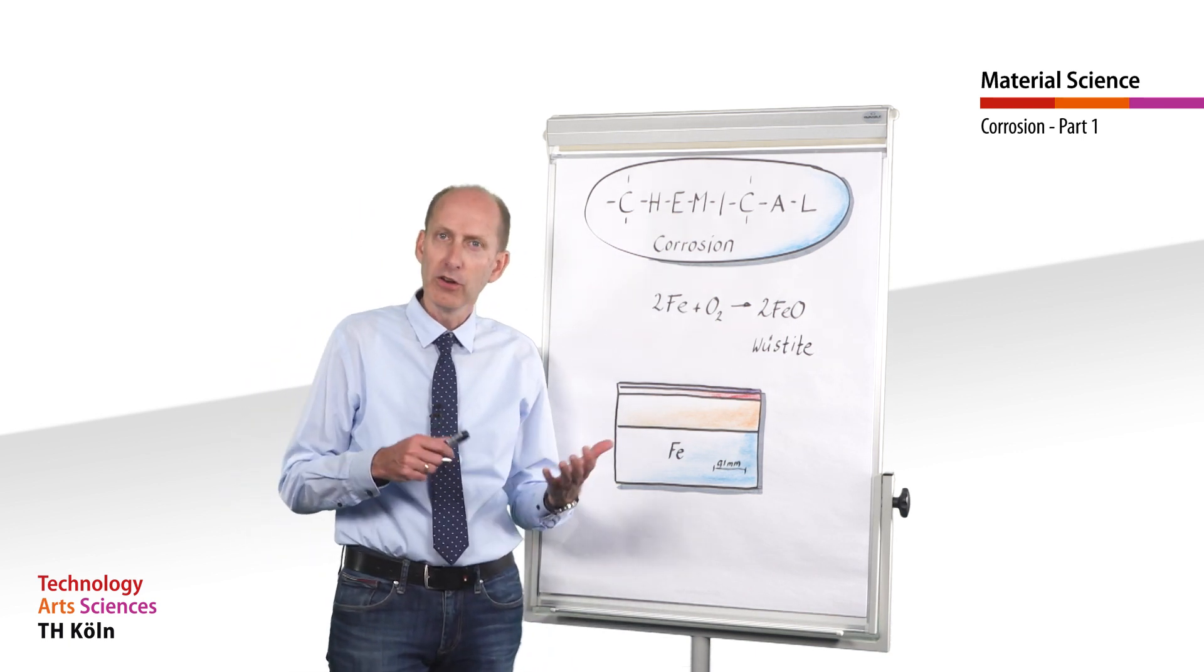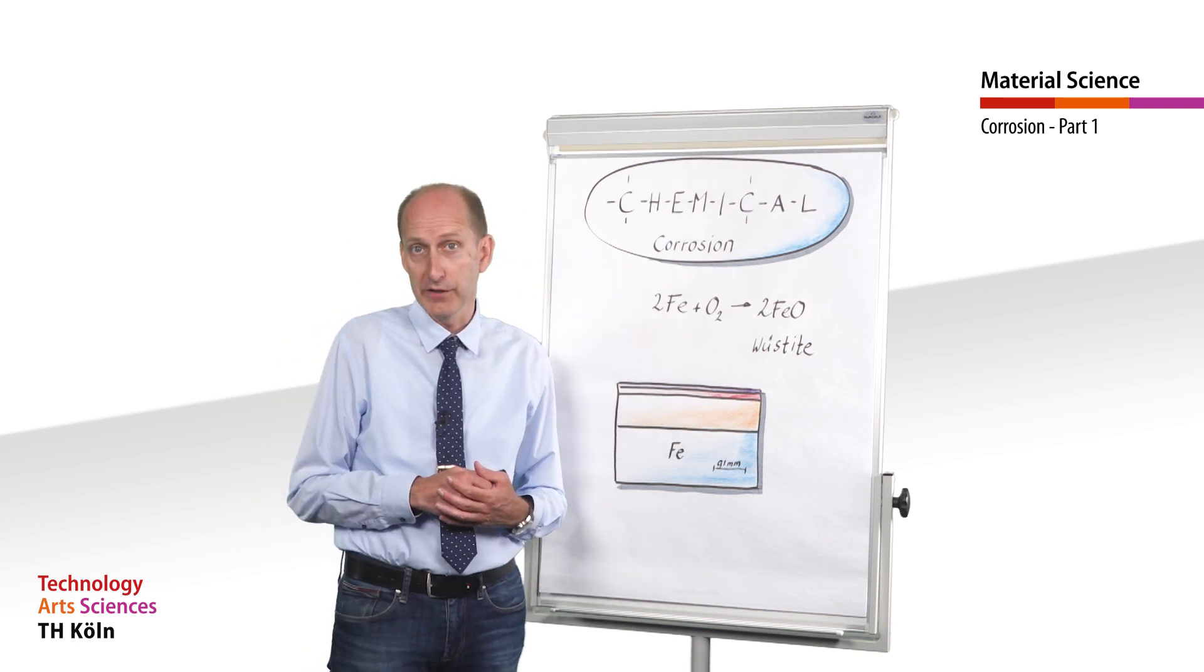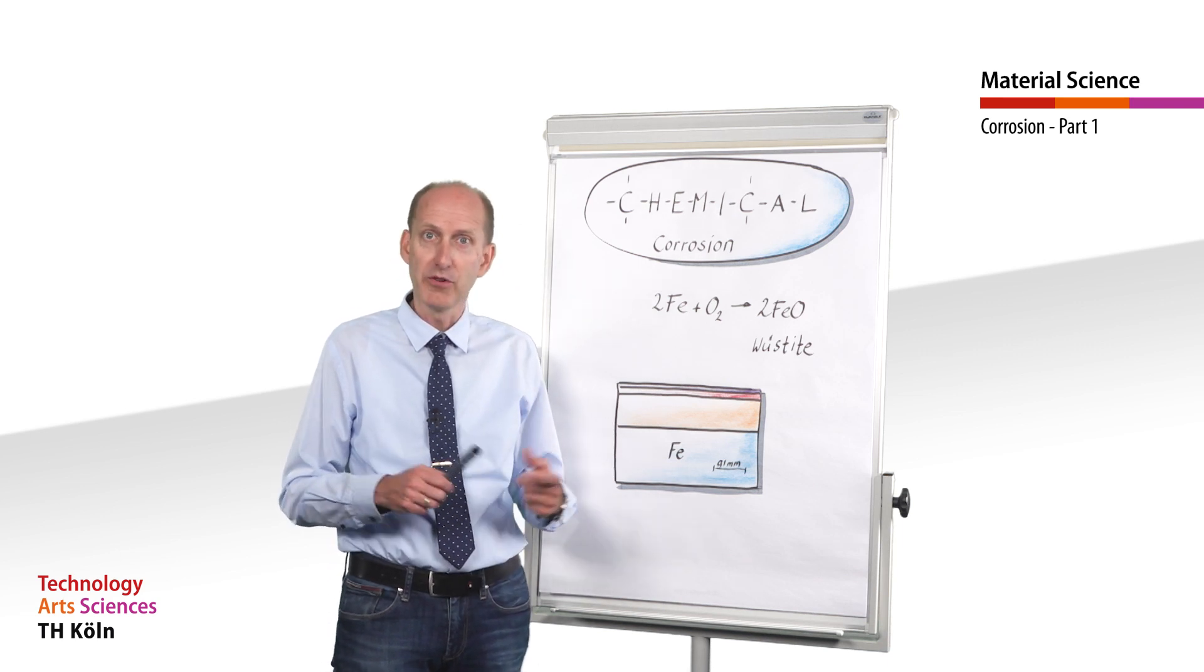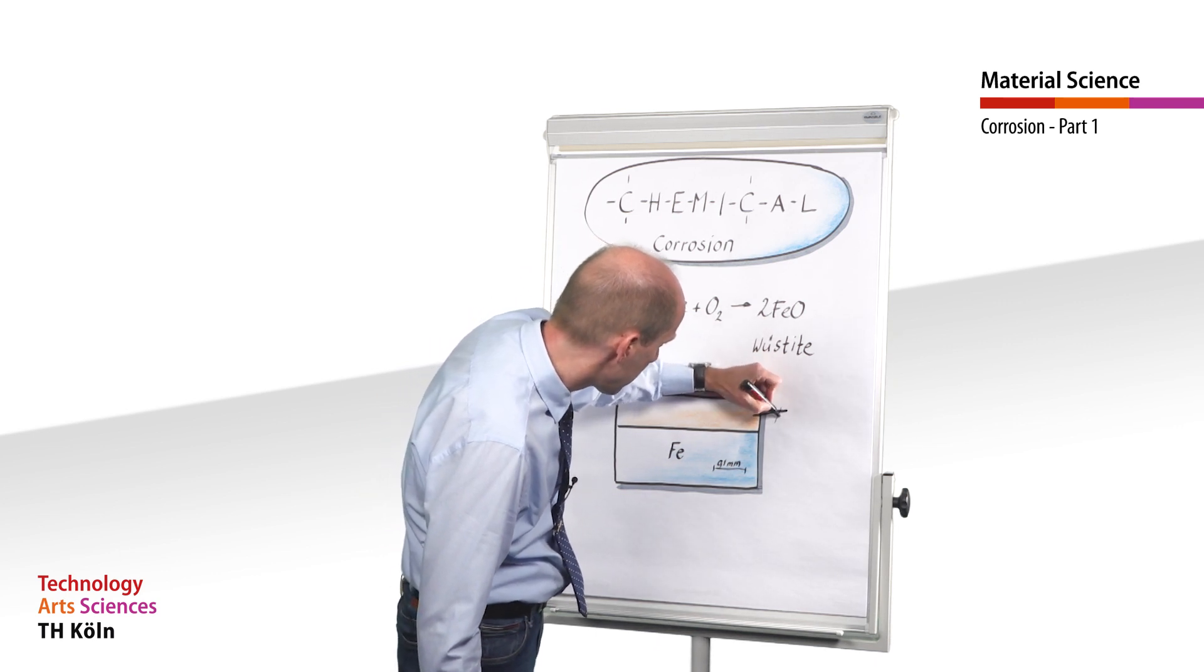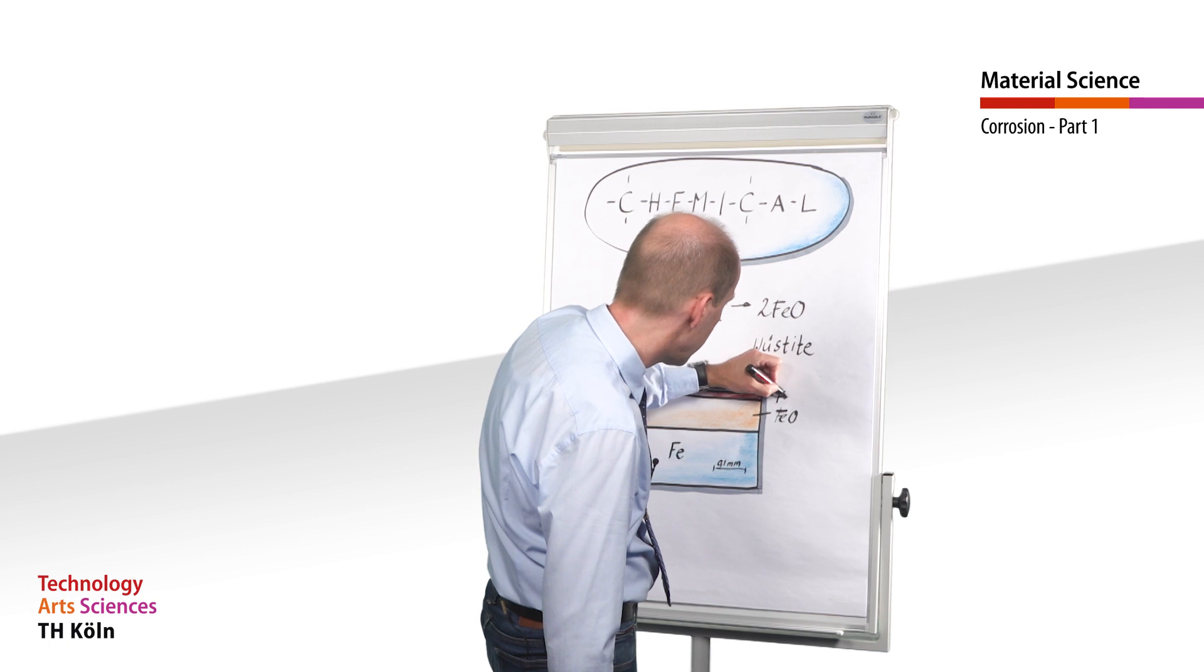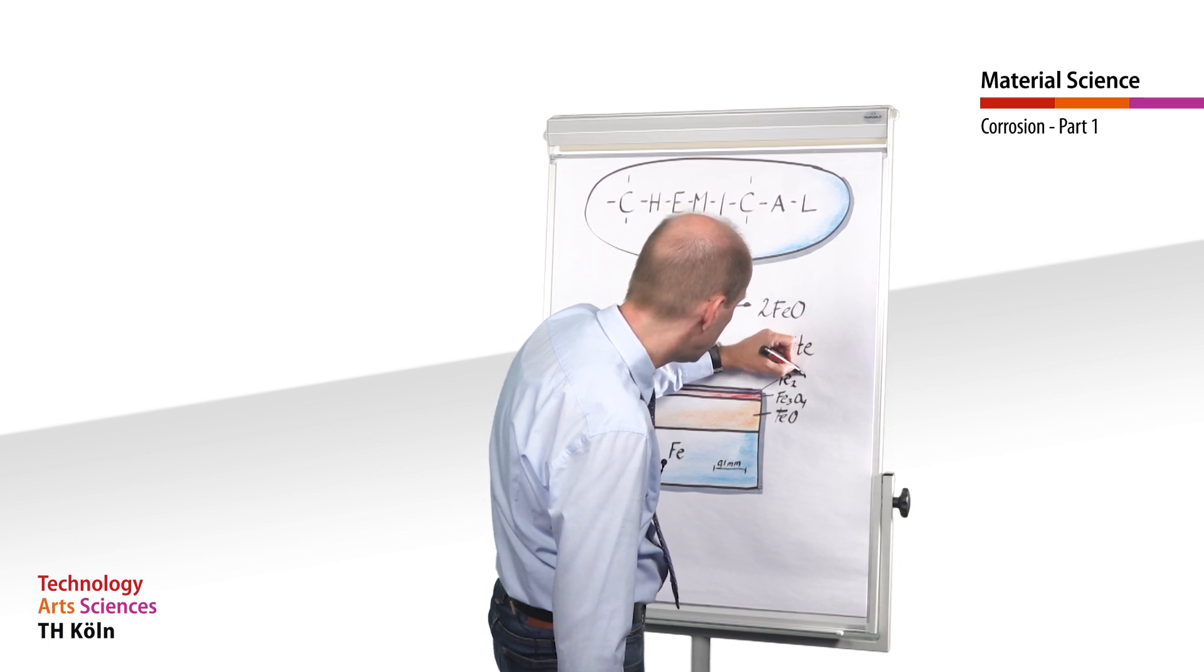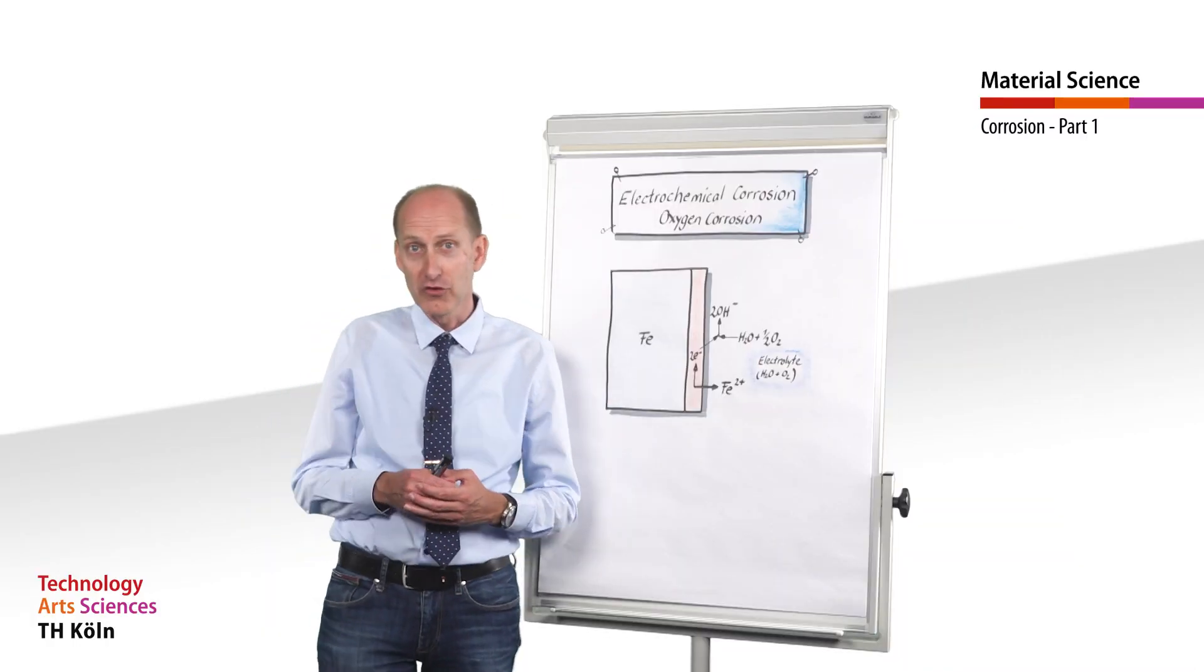Let's take a look at how an unalloyed constructional steel, which was aged for 72 hours at 650 degrees Celsius, would react with oxygen. In addition to the primary Wüstite layer, this one here, FeO, further reaction to magnetite Fe3O4 and finally to hematite Fe2O3 takes place.